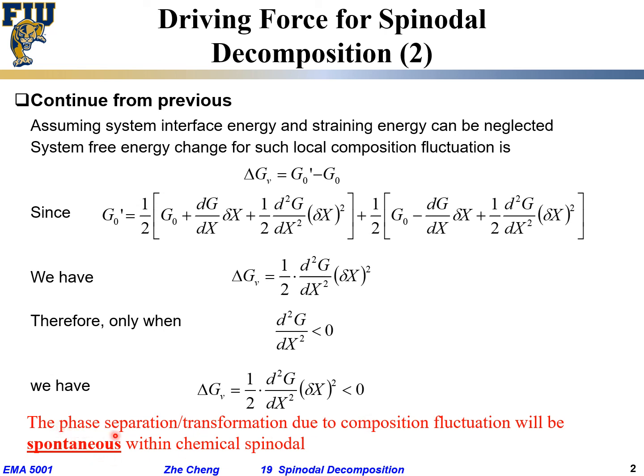The phase transformation or phase separation from one single uniform phase to two phases — one with composition x0 + delta x and one with x0 − delta x — will be spontaneous only when the Gibbs free energy decreases. This requires that the second-order derivative d²G/dx² is negative, which means the system is within the chemical spinodal, i.e., within the inflection points.